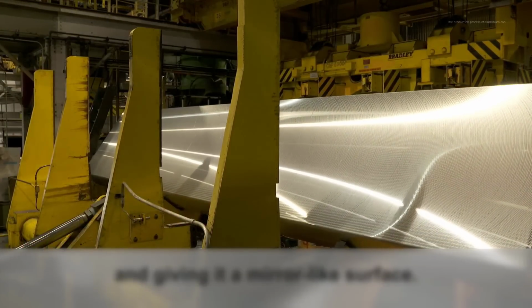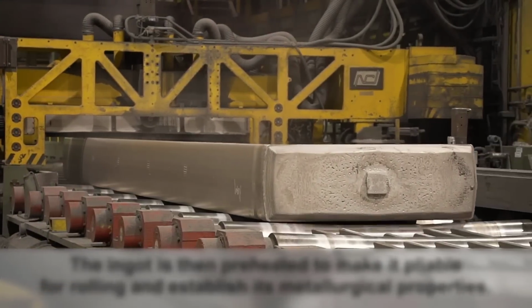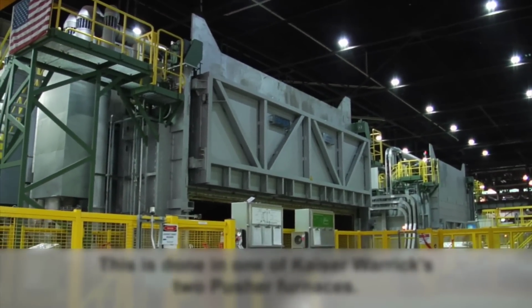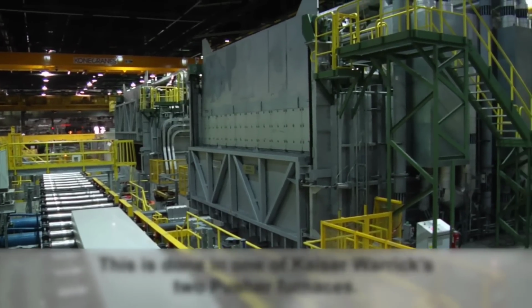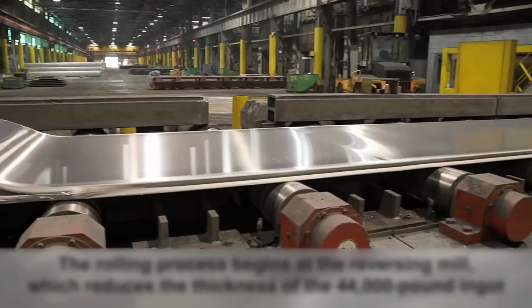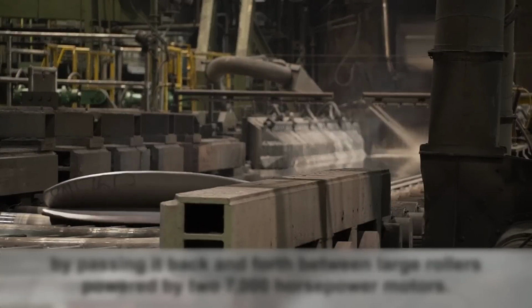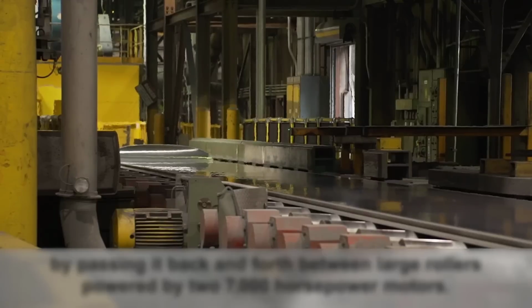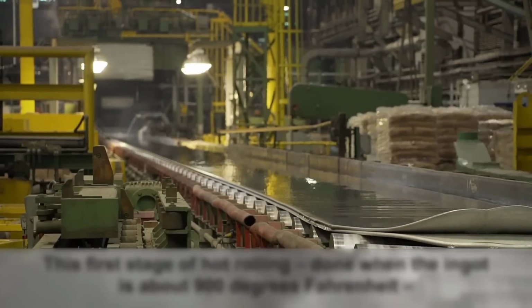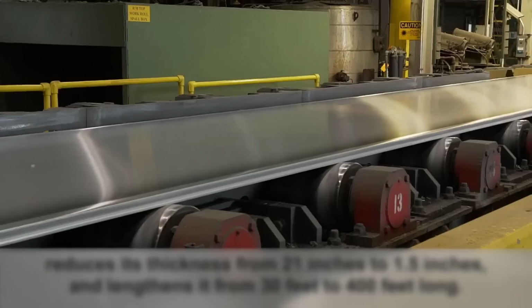To prepare the ingot for rolling and establish its metallurgical properties, preheating is performed. Kaiser Aluminum Warwick employs 2 pusher furnaces for this purpose. Once pliable, the rolling process commences at the reversing mill. Large rollers, powered by 2 robust 7,000 horsepower motors, reduce the thickness of the ingot through a back-and-forth motion. The initial stage of hot rolling, executed at temperatures around 900 degrees Fahrenheit, leads to a reduction in thickness from 21 inches to 1.5 inches, while also elongating the ingot from 30 feet to a remarkable 400 feet.